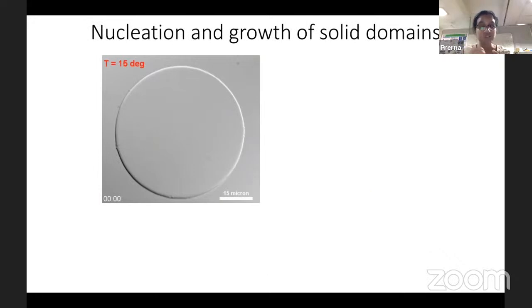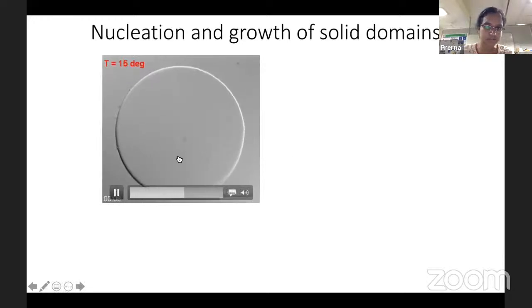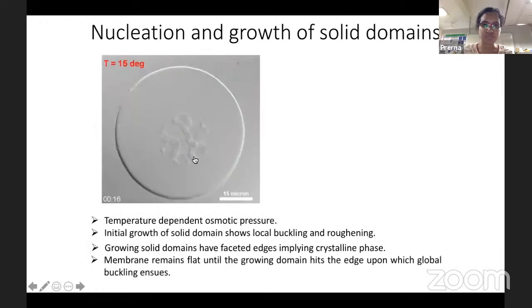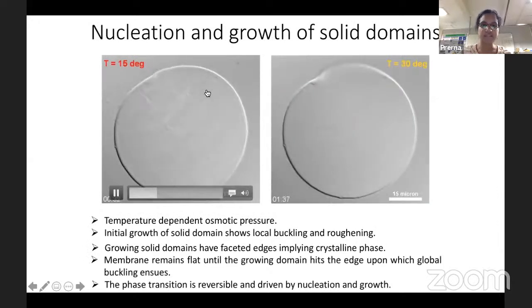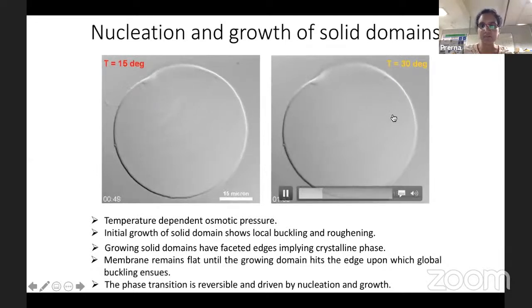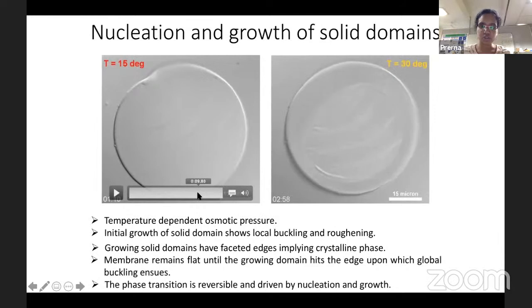If you want to really know how you can go from a fluid phase to a solid phase, you really need to have another parameter. To watch the kinetics, we take a polymer whose osmotic pressure is temperature dependent. Here I will induce crystallization by lowering the temperature. What you can see is that a crystal nucleated, and this crystal is spontaneously wrinkling. If you let it play on, it will just grow and then cover up the entire sheet, and then the sheet can melt again if you increase the temperature. So here you're going to increase it again, and you will come back to the fluid phase. So I've shown you both the transitions.